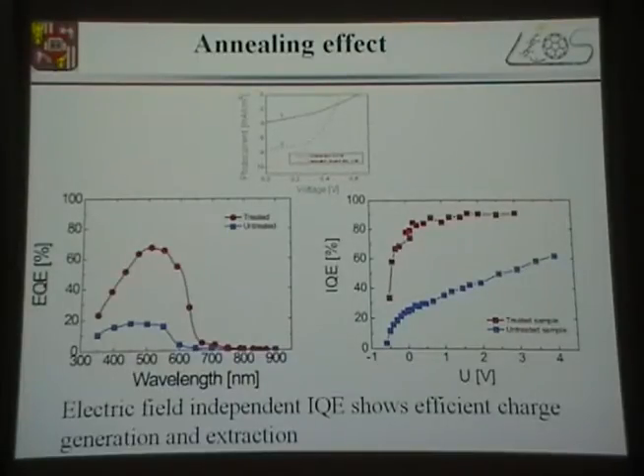So we simply took an as-spun solar cell and an annealed solar cell. The annealed solar cell is around 4%, something like that. And here we see the IPCE or the EQE data as a function of wavelength. But what is actually interesting, here you see the electric field dependence of the internal quantum efficiency. And you see here that for the efficient solar cells, the internal quantum efficiency becomes electric field independent, showing that most of the charge transfer states or most of the photoexcitations are efficiently split and transported to the electrodes, whereas the inefficient solar cell has a very significant dependence, as has already been shown by Lydia.